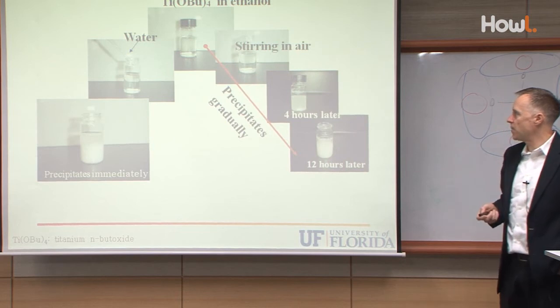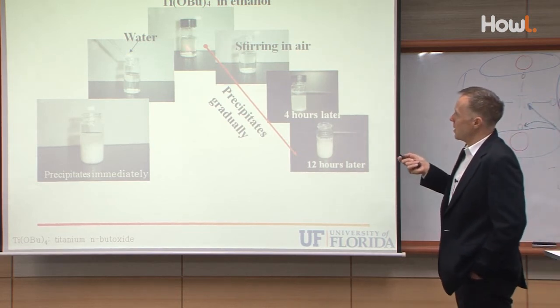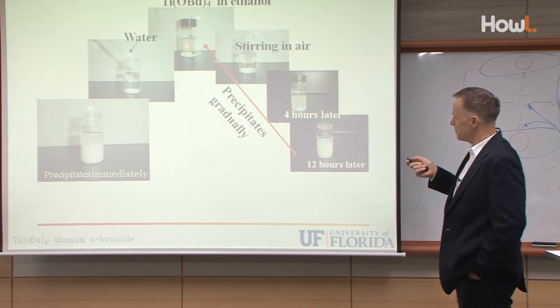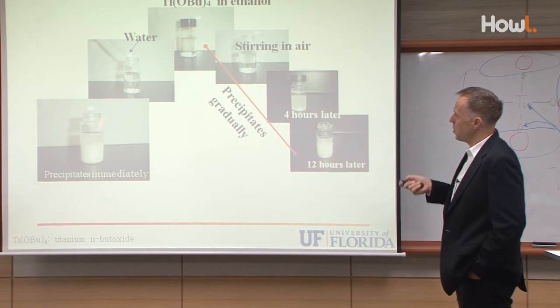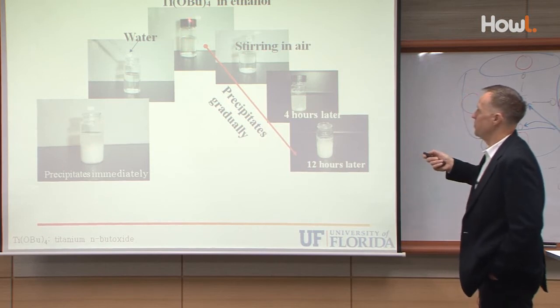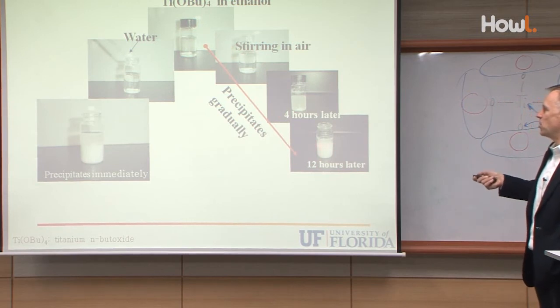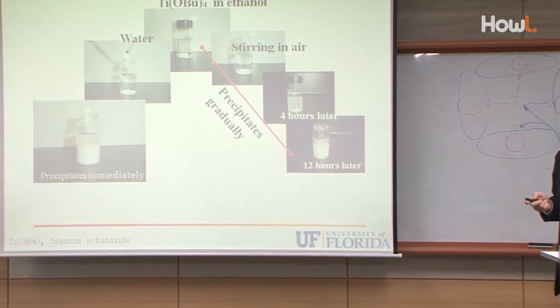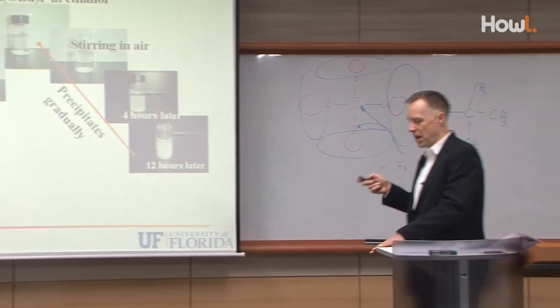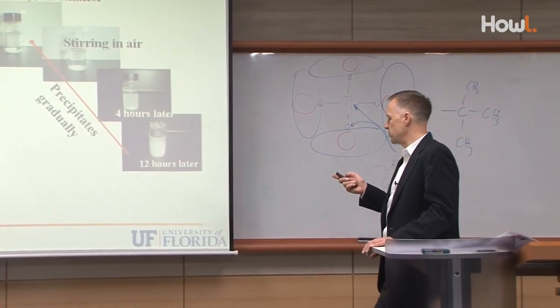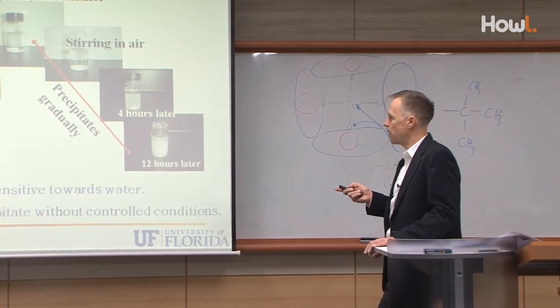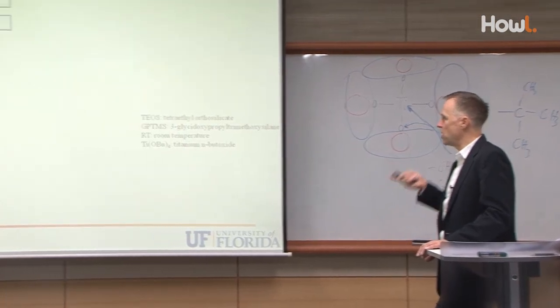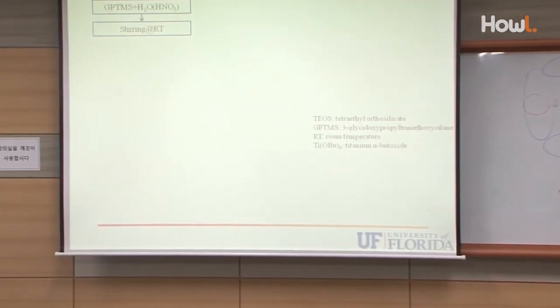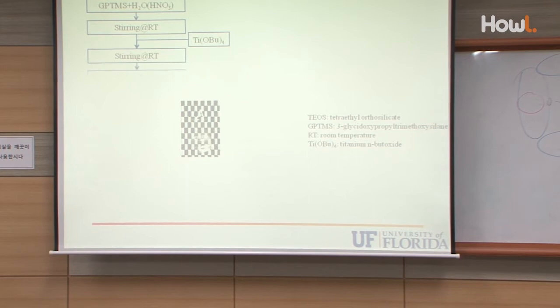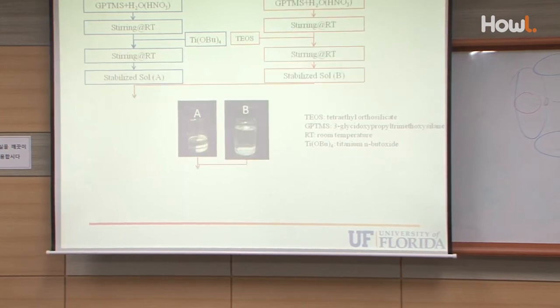And here's just the picture of what happens. Titanium isobutoxide, titanium butoxide in ethanol: if you add water, immediate precipitation, of course. If you keep it open in air, in just 12 hours, it's precipitated. And if you have it in a syringe, even sealed, because you transport it through air, you expect it to precipitate within maybe 3 or 4 days. So we have to do something about this, and you can then do colloid science, chemistry, combined systems. And I'm just clicking through a little bit faster here.